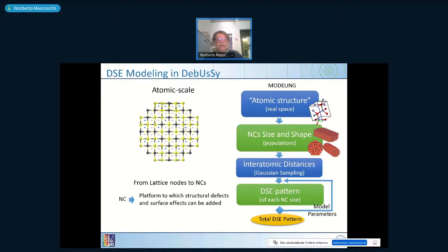You compute within each item of the population the interatomic distances. There are some tricks which speed up the calculation called Gaussian samples. Then you calculate the DSE pattern of each crystal size. You sum up the different patterns depending on some law, for example, the log normal distribution seen before, and you calculate the total DSE pattern. Now you match the total DSE pattern with the original data. There will be certainly some mismatch. You try to modify in an iterative way your parameters, for example, shrinking or enlarging the unit cell, changing the number of large clusters versus small ones. So you have different model parameters, and you can just match versus the observed data.